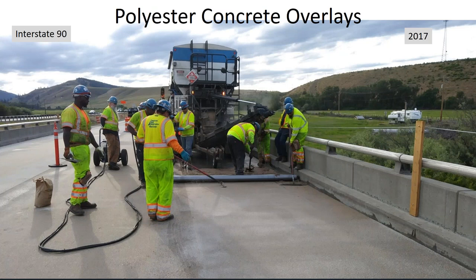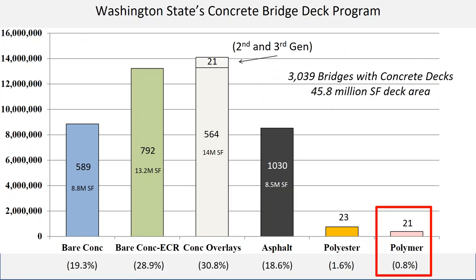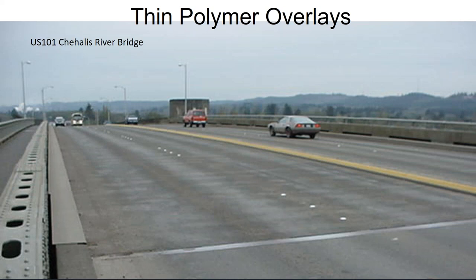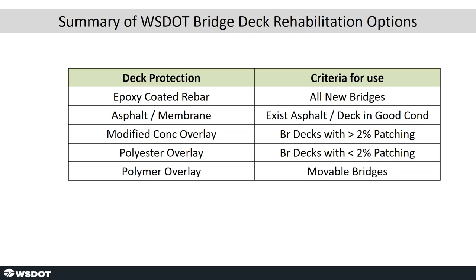Here's a contractor kind of completing up a polyester overlay on Interstate 90 outside of Ellensburg last year. Then polymer overlays. Polymer overlays, we tried a lot of them, but with our studded tires, they became smooth after about 5 to 7 years. We're still using polymer overlays on movable bridges.